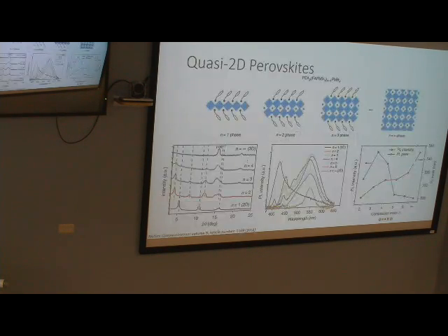In this talk, they found quasi 2D perovskites to be a really strong emitter of green emission, which I'll show in a minute. Here they used varying layers of perovskite structure. The blue octahedra is the PbBr6 cage. They used phenylethylammonium with a formamidinium composition as the A cation. When we look at this figure, all the way to the left, this is the X-ray diffraction.